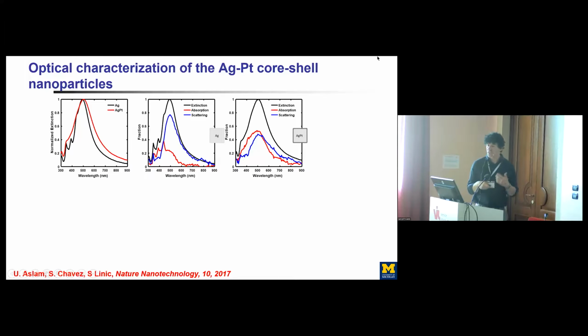And this is now how these silver platinum nanoparticles respond to light. So this is, again, silver and silver platinum. You see the extinction spectrum of both. And now you can monitor, using an integrating sphere, absorption versus scattering. In the case of silver, as I said before, when you have large nanoparticles, you expect most of it to be scattered into the far field. And that's actually what's happening here. You see a large fraction of this extinction is due to scattering. In the case of silver platinum, you actually see that you have much more absorption compared to pure silver, because again, you are introducing this very small amount of platinum on the surface of the silver.